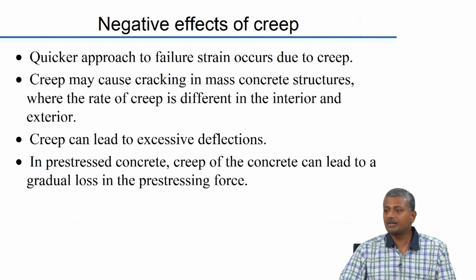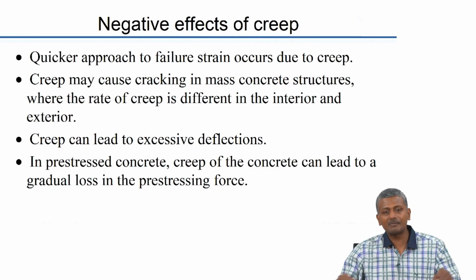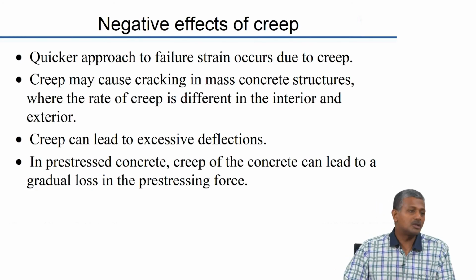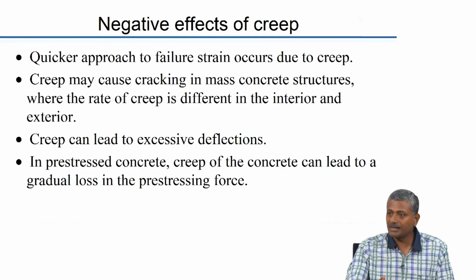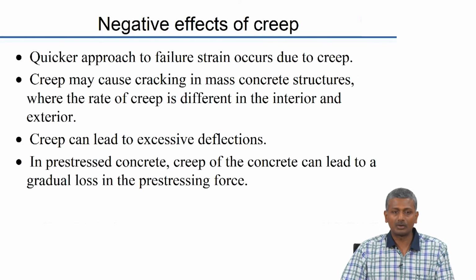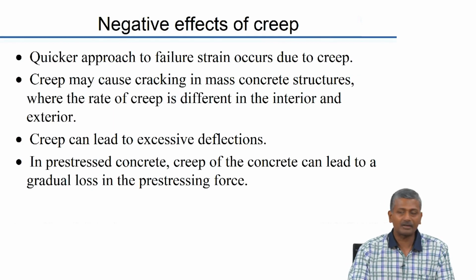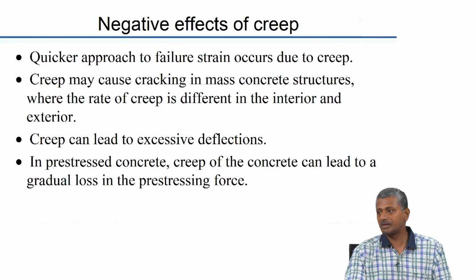In pre-stressed concrete, creep of the concrete can lead to loss in the pre-stress force. So, you do not have the same effectiveness maintained throughout the performance of your pre-stressing member. Okay. So, you need to account for those pre-stress losses beforehand by understanding the extent of creep coefficient that you have in the concrete, and this can be a valid factor in the design of pre-stressed concrete members.